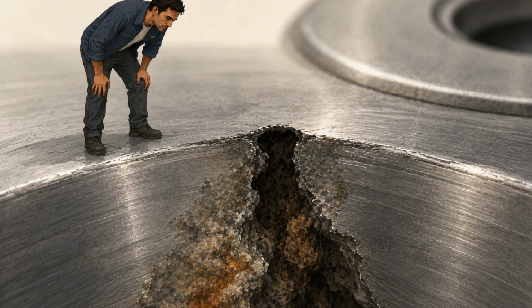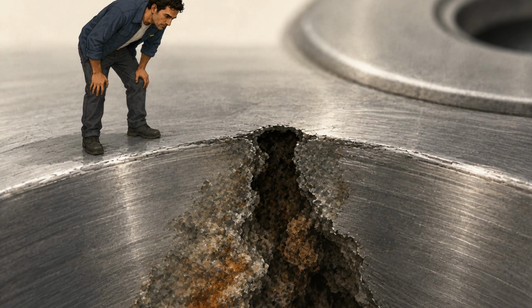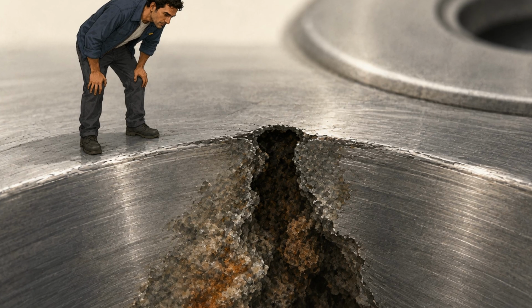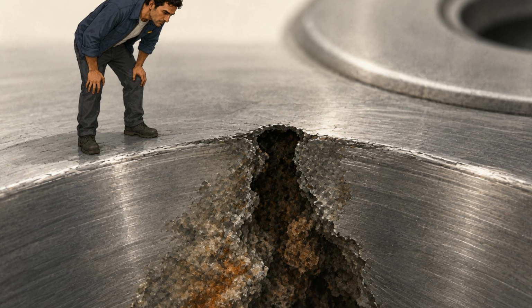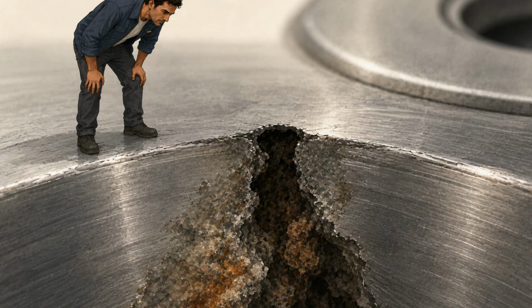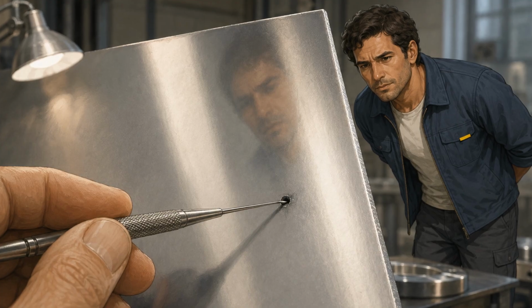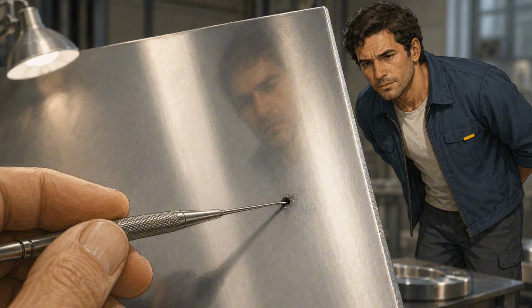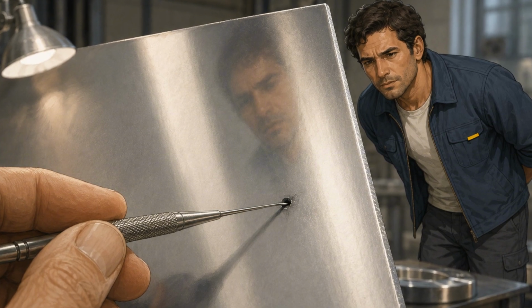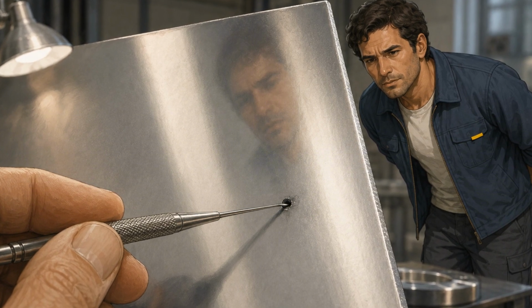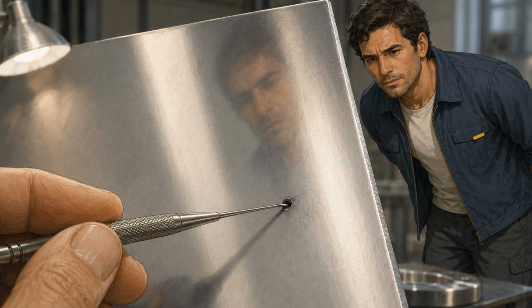This is crevice corrosion. Pitting follows a related local feedback. Chloride breaks down a vulnerable point, and the tiny cavity develops chemistry that drives attack deeper into the metal. That is why stainless can fail without turning uniformly red. A polished sheet may look sound around one dangerous pit. The visible shine can hide a highly local problem.